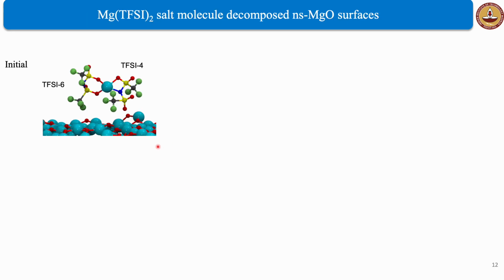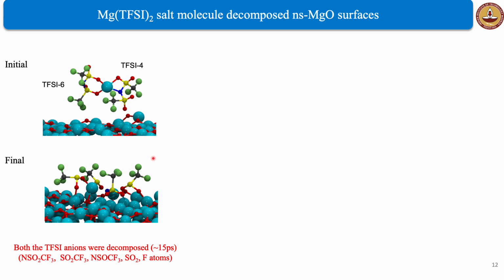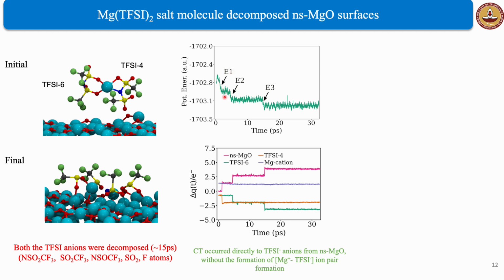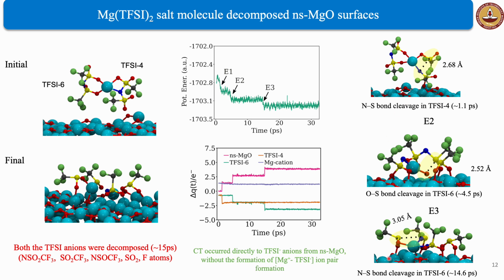Next, we move to the ns-MgO surface. Here, unlike the metallic Mg and stoichiometric MgO, both the TFSI anions decomposed within the first 15 picoseconds of the simulation, leading to various fluorine-containing decomposition products, in line with the experimental findings. Here, the potential energy profile exhibits three sharp drops, each marking a major structural change, E1, E2, E3. Also, a significant amount of charge transferred from the surface to the TFSI anions, leading to the cleavage of bonds such as N-S, O-S, etc. These are the three major structural, decomposition events.